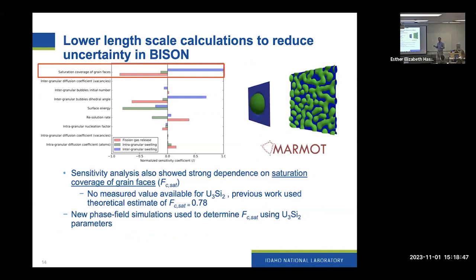And so what that parameter is: if we have a certain fractional coverage of the grain boundaries above that saturation value, essentially the Bison model assumes that all of the gas bubbles become interconnected and the gas can then be released into the fuel cladding gap. So they didn't really have a measured value available, so they were using a theoretical estimate, which is basically, how many circles can you pack into a square? So it's basically pi over four. But the reality is the microstructure is much more complex.